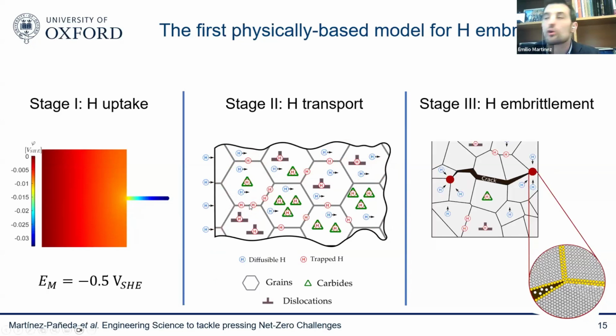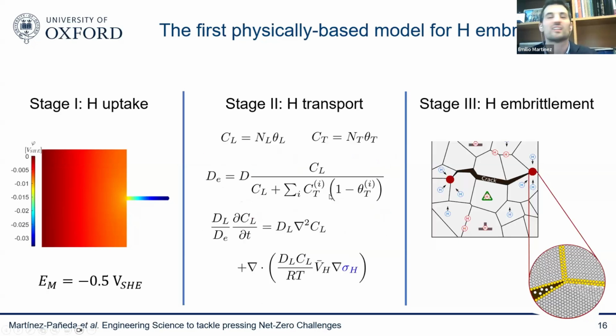sequestered at specific locations, specific defects, such as grain boundaries, dislocations, carbides, which is what we represent here. And we have, again, models for this. These are extended versions of Fick's law. You will remember Fick's law from any other transport model that you have done during your undergrad, and you will remember that this, again, is based on properties that we can measure: diffusivity, again, temperature, this we know. There's some binding energy related to the defects. Everything we can measure independently in the lab.